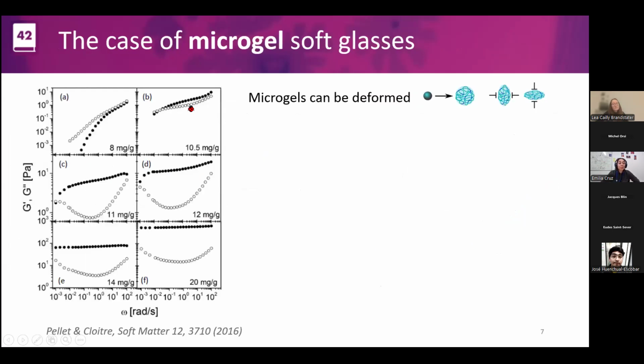So a good way to illustrate this is the case of microgels. Microgel glasses. There's this really nice example by Charlotte Pellet and Michel Cloitre, in which, because microgels can be deformed, they prepare a microgel dispersion. And you can see that there's different concentrations. And here it's a frequency sweep.